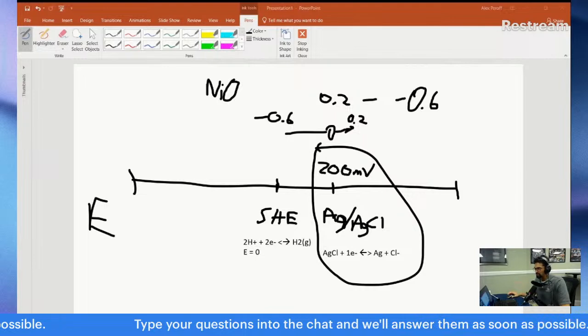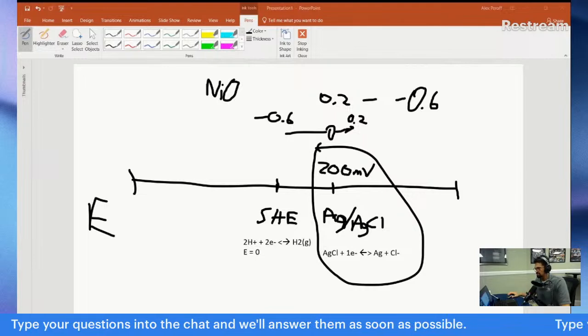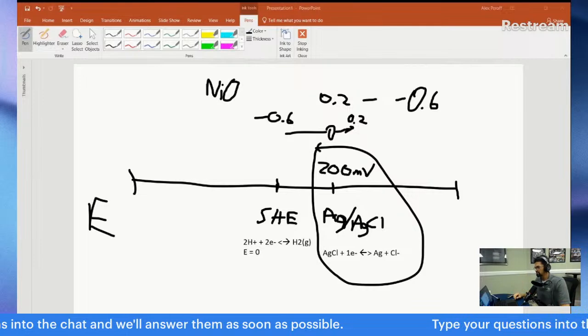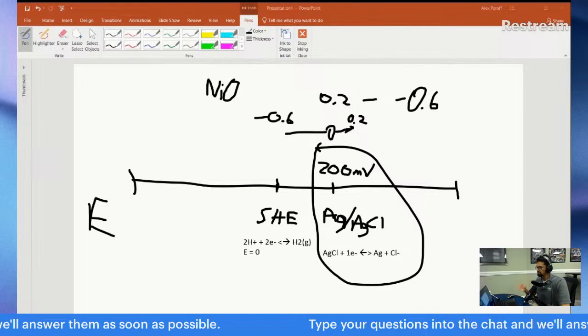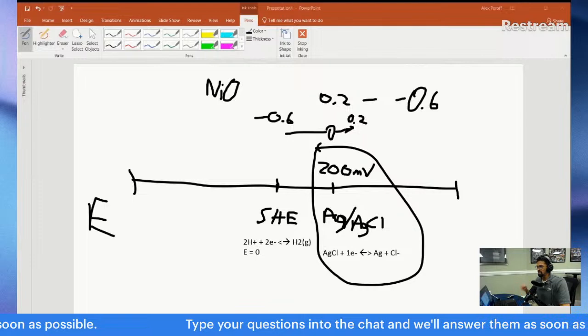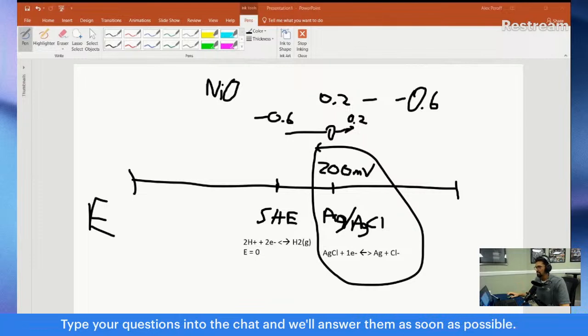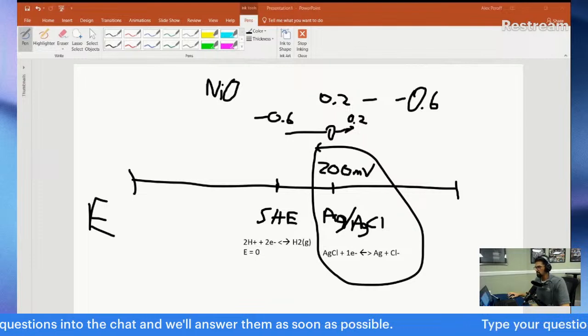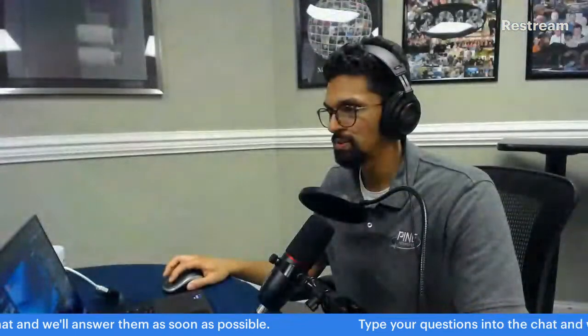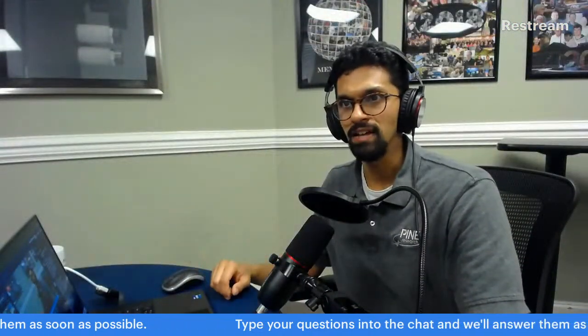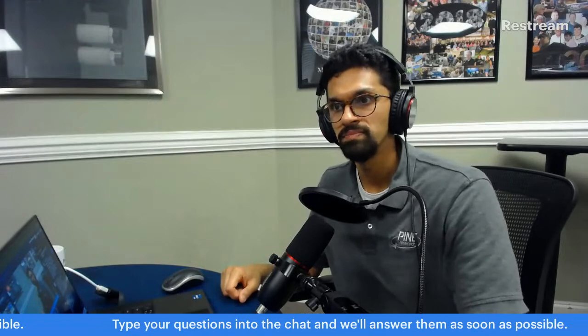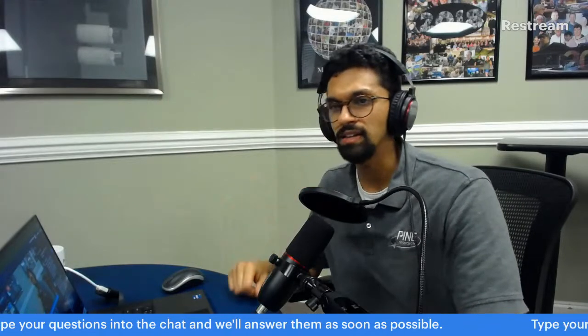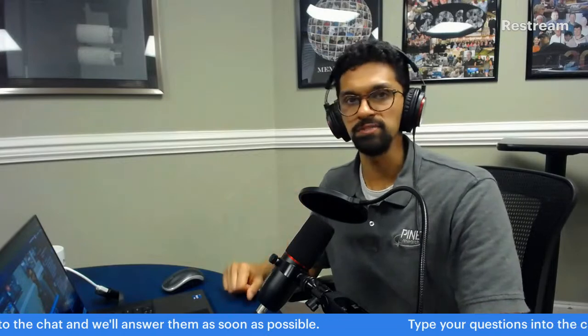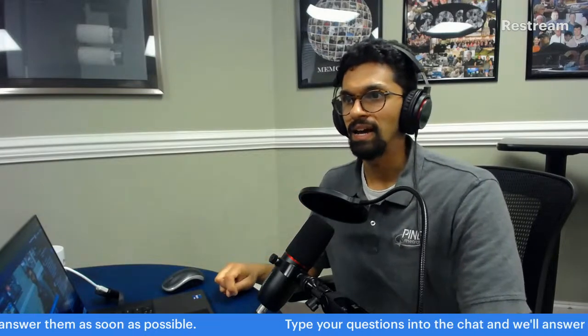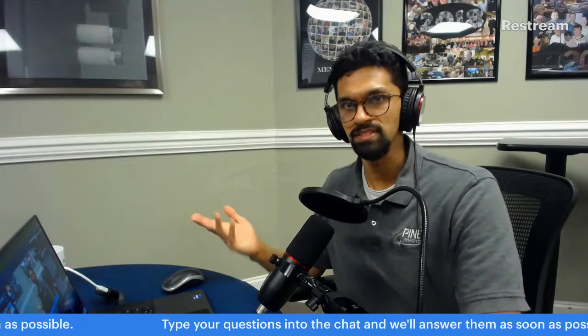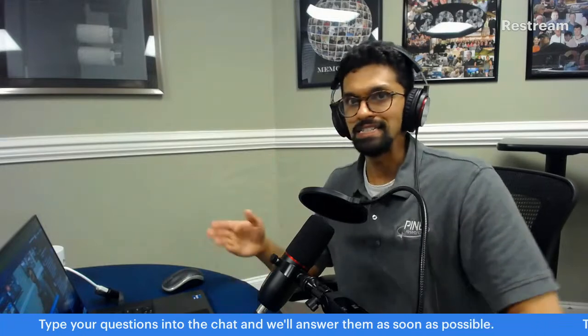And really, the only way to determine this, Sadaf, is that you need to do the experiment with and without the nickel oxide. And if you do the experiment without nickel oxide and you don't see those redox peaks, then it's most likely the case that those redox peaks are associated with nickel oxide, and that the oxidation reduction process that's happening of your nickel oxide is within that